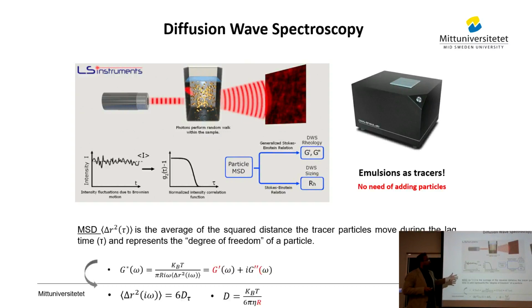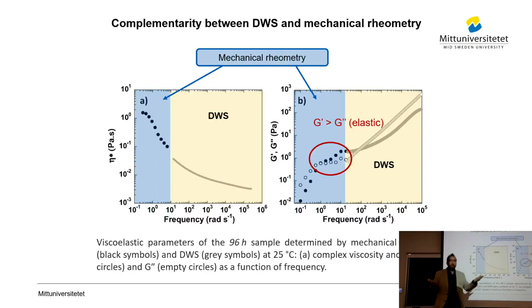That was quite nice to characterize these cellulose-based emulsions, which had not been done before. And just to illustrate, I believe you are familiar with normal mechanical rheometry, but it has a hardware limitation that we cannot access larger frequencies. We cannot just oscillate forever. So with this optical light-based method, we can access much higher frequencies, and we can complement both the mechanical and the optical properties, checking the storage and the loss moduli and so on. So it's a nice technique to characterize these emulsion-based systems.